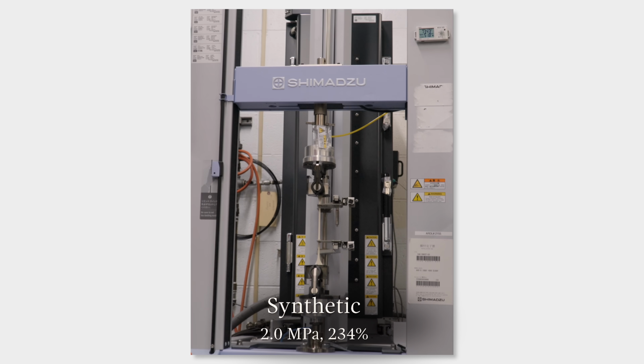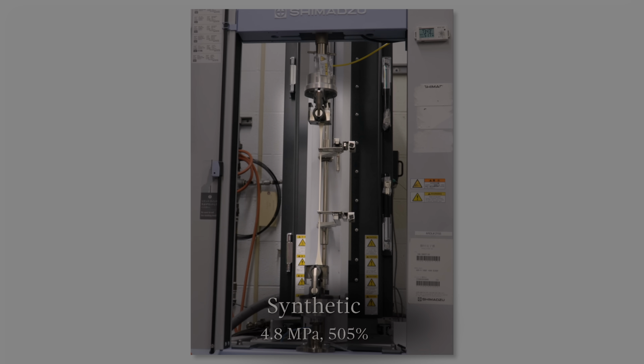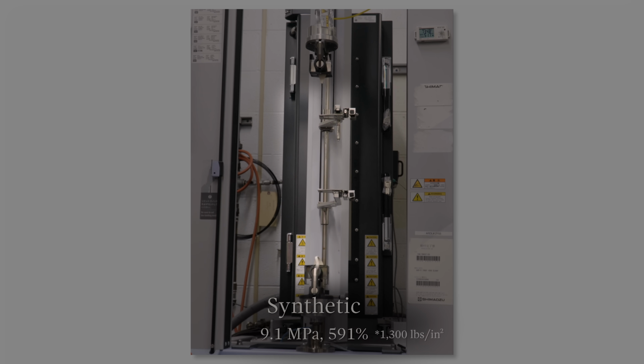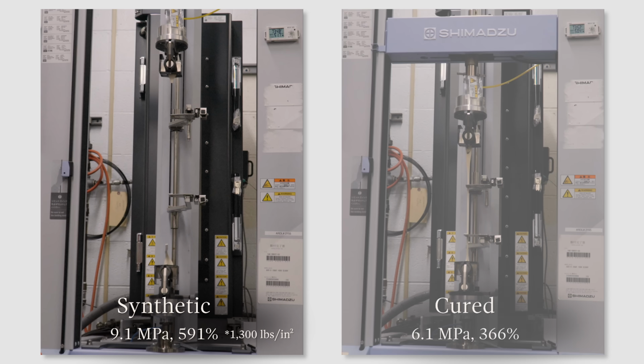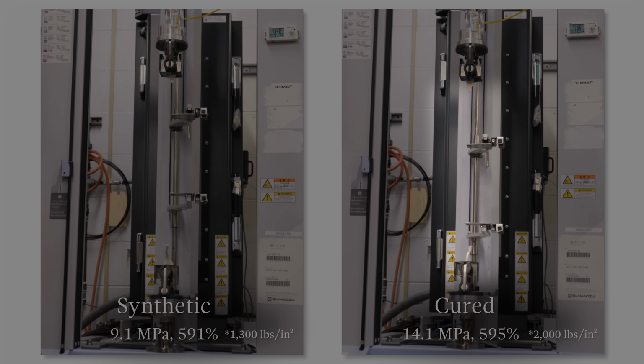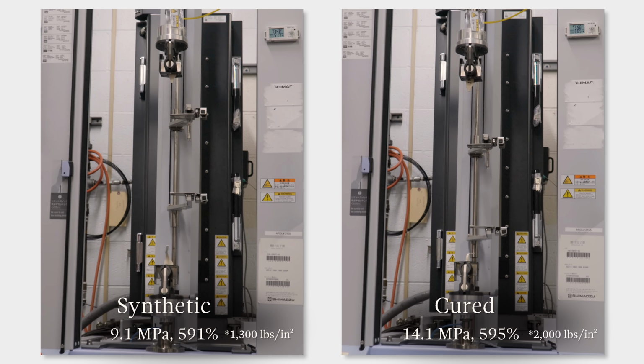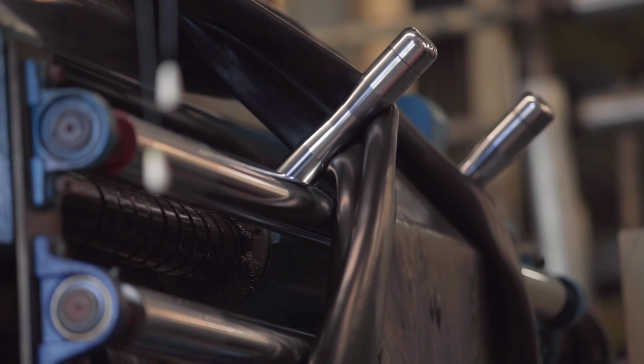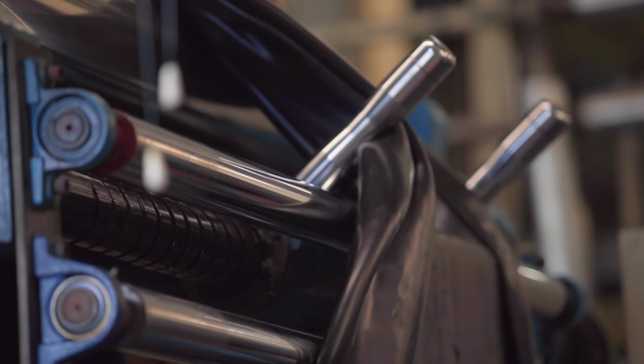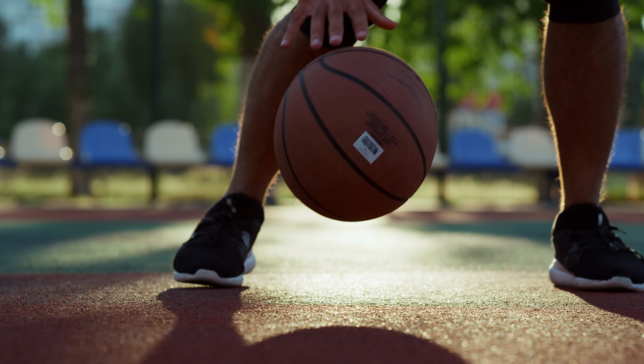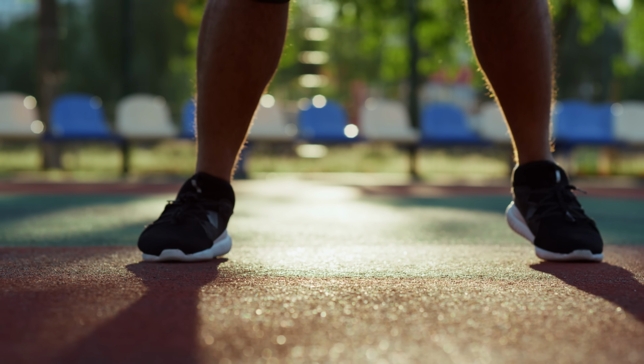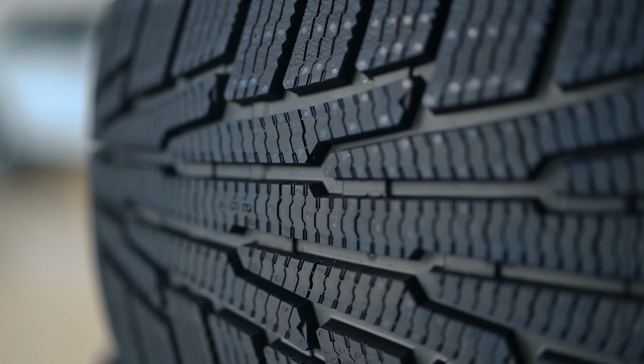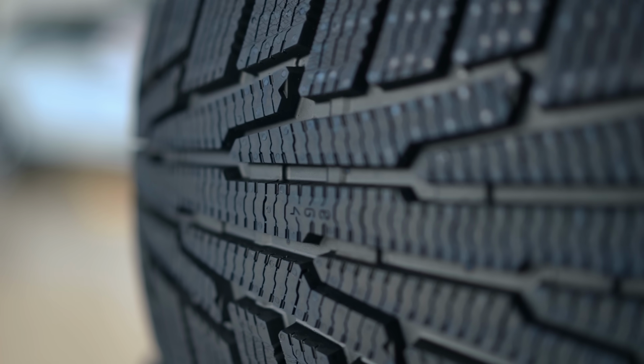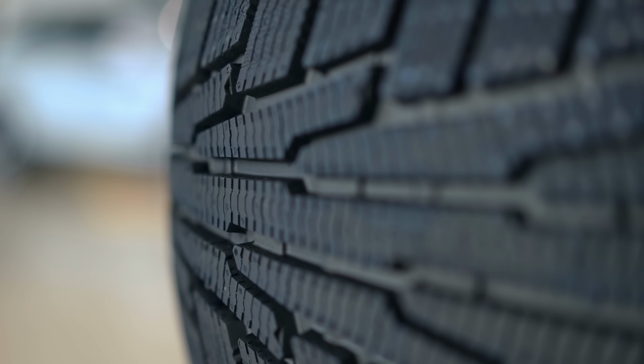In a tensile test, a synthetic rubber also stretched to around 600% before breaking, but it only took around 9.1 megapascals compared to over 14.1 megapascals for natural rubber. But there are a few areas where synthetic rubber is actually better than natural. Under low stress, where crystallization doesn't happen, natural rubber loses the advantage, so synthetic is preferred for the tread of passenger car tires for better abrasion resistance.